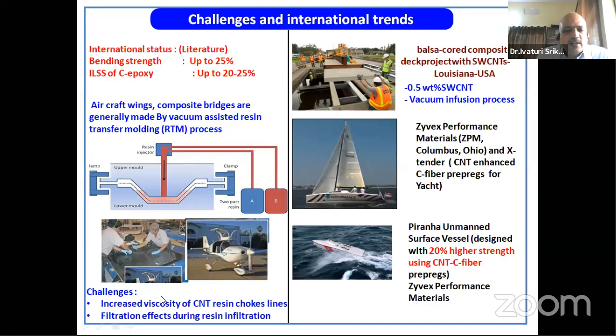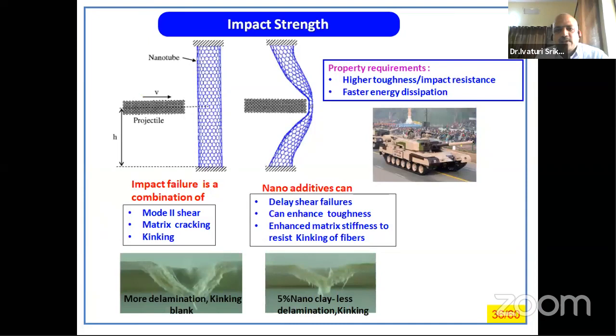Prepreg is a resin added fabric which is semi-cured, and you need not apply any resin further. Straight away you take it, lay it up and then cure it. That is called prepreg. So CNT added prepregs were used globally to overcome the processing issues, and people have reported up to 20-25% improvement in mechanical properties for various systems. So compared to tensile, flexural improvements are definitely possible, but again, it depends on the fiber volume fractions that we are looking at. The next one is impact property.